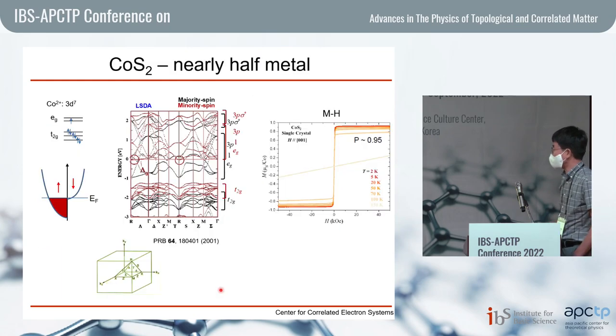This cobalt disulfide was known to be nearly half metal. Cobalt is in 2+ state again, 7 electrons in 3d. So there is only a single electron in the eg orbital. And if this is fully polarized, you can expect that only the majority spin is occupied and the minority spin